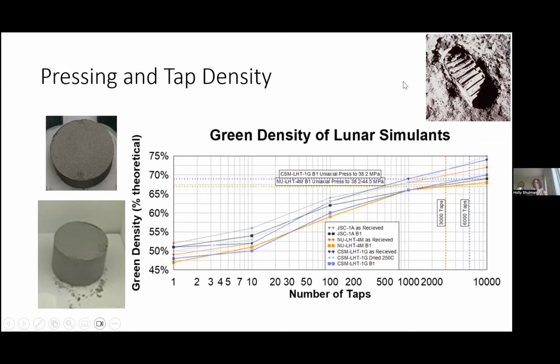And on the right, I'm showing the iconic footprint that shows that you really would be, of course, with very little pressure, able to form these in a green state very easily. Normally, for most ceramics, you need to add some type of organic binder, which you then burn off later. But because of the ISRU restrictions, I didn't want to use any binder. And I was able to press, these are like 2-inch diameter pellets, pretty good sized pellets without any problem at all. And we did this on many different types just to understand how we're going to form these things.